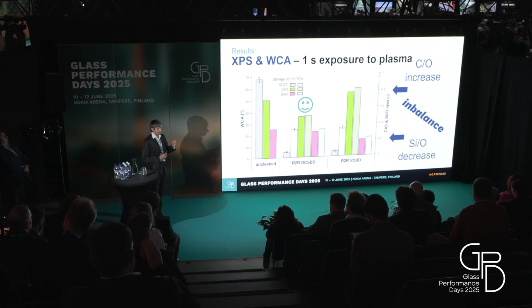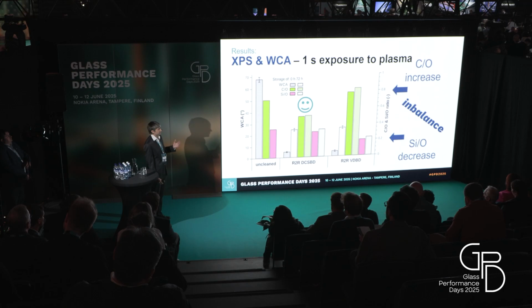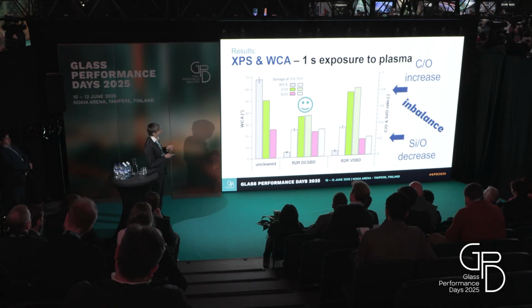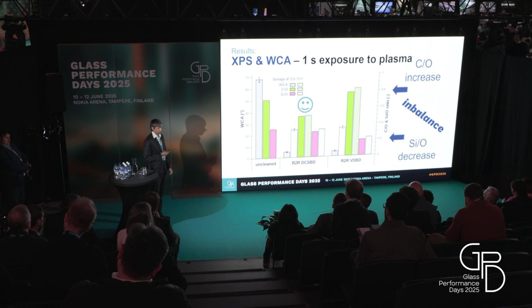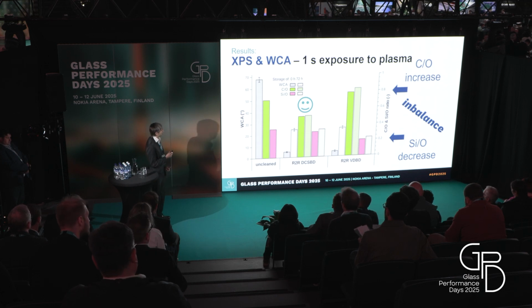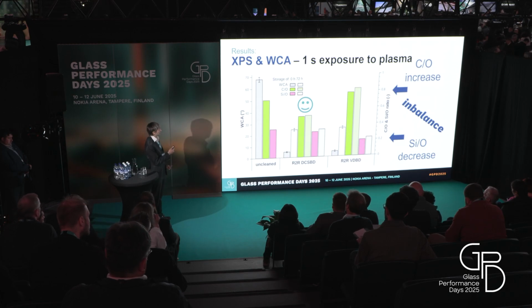So some material is appearing on the surface, so Si/O is lowering. So this was for the plasma source which has volume DBD, but for the DCSBD plasma source it was pretty stable, and similarly as in the reference sample it was not very changed.